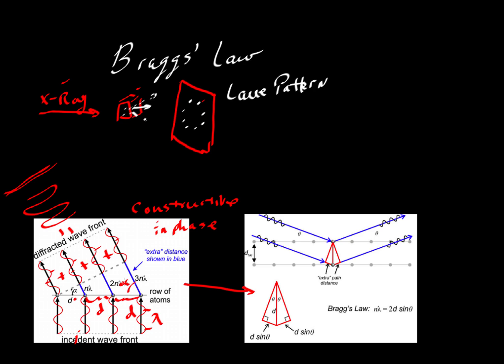What if you pick some other value of alpha? What if the diffracted beams are coming off at some other angle that's different from the special angle? Then the peaks and troughs will not line up. We don't get the constructive interference. Instead we would get destructive interference and the detector is not going to see this large burst of energy. So that would be these black spaces in between. We have the special relationship between alpha, lambda, and D.